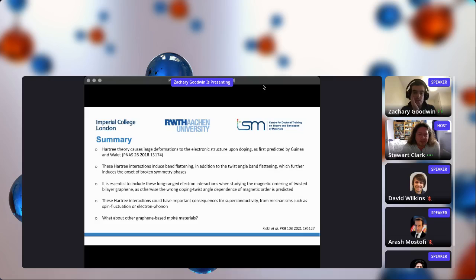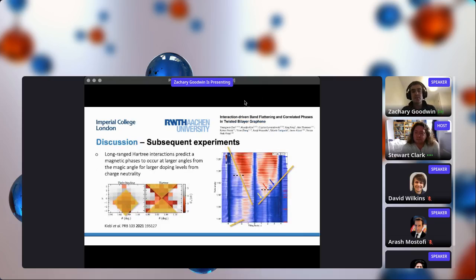Yeah, so there's two factors with that. In the experiments, they have the twisted bilayer graphene mounted on hexagonal boron nitride. And so there's an additional degree of freedom, like what twist angle do I decide to introduce between the graphene layer and the HBN. Because if I align it, there can be C2 symmetry breaking, which can have quite a big influence. But if you introduce a large twist angle between the graphene layer and the HBN, the effect of the substrate in that sense is quite weak. Explicitly, you probably should have the double moiré pattern, but this increases the computational expense because you have hundreds of thousands of atoms in your moiré unit cell then.